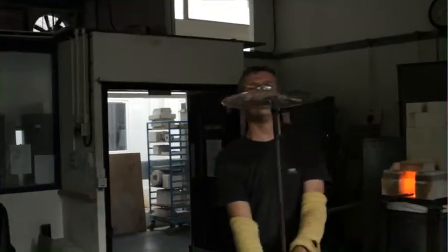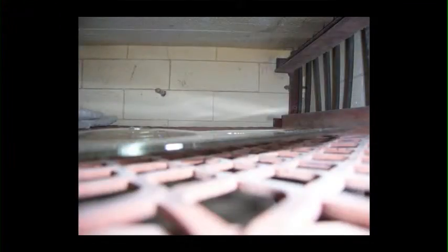The vessels that I made were thinner than anything I've made before. They bowed in the leer. At first I thought I may have been mistaken with my annealing temperature, or that I was putting the plates in the leer too hot, but they bowed upwards rather than slumped down. It seemed as if they were so thin they warped, like ceramic plates sometimes do when fired.